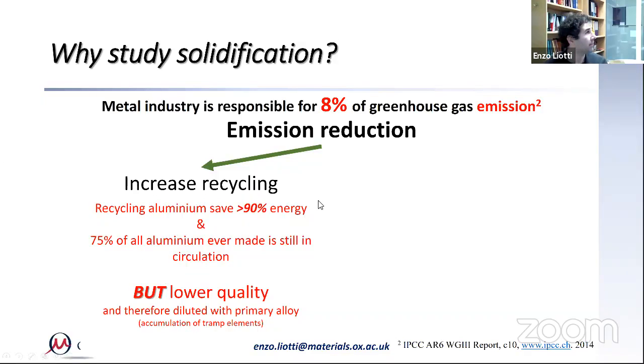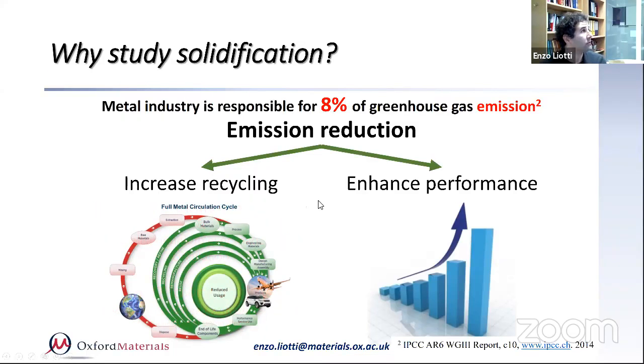So that's not a demand problem. And the second possibility is to enhance performance. Both of these criteria are heavily dependent on solidification. If you get a material with a very good microstructure with a lower level of defects at the beginning, then you will have better performance. And if you can control solidification wisely, you can probably reduce the need of diluting the alloy.